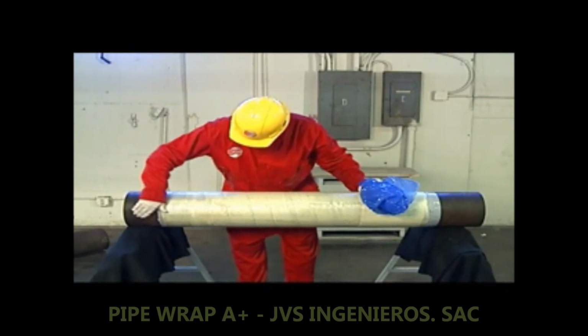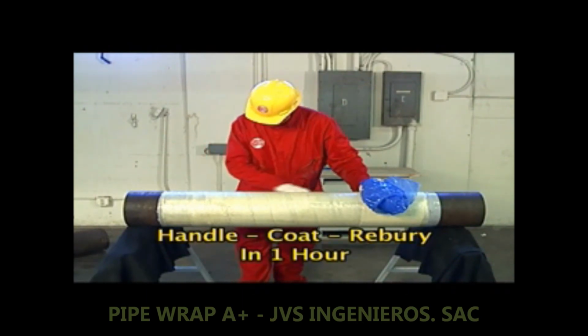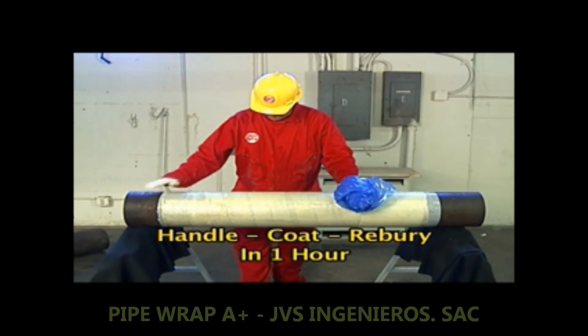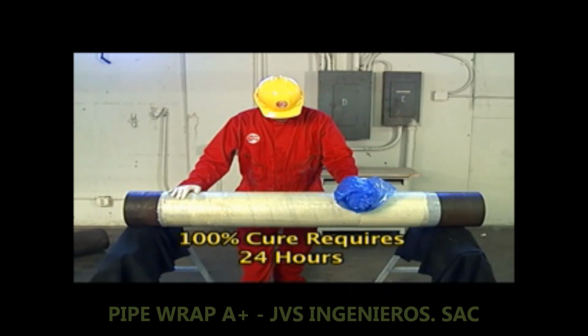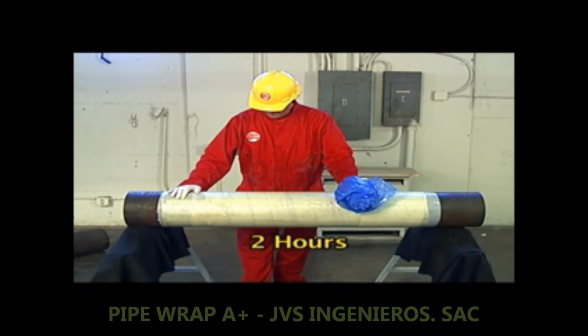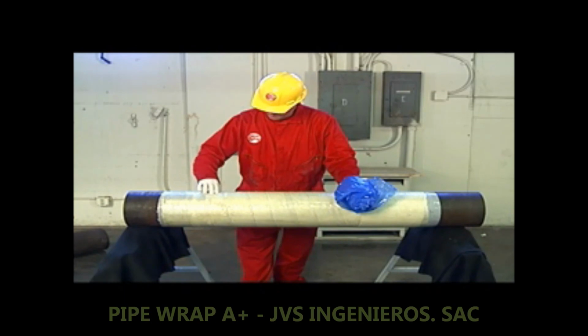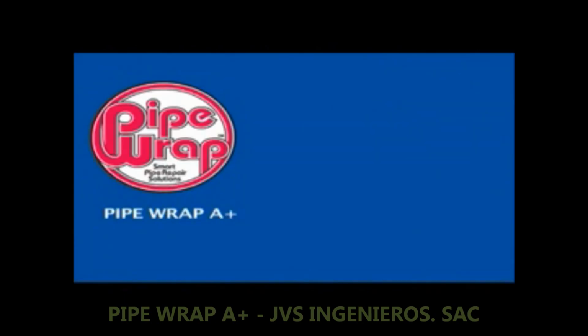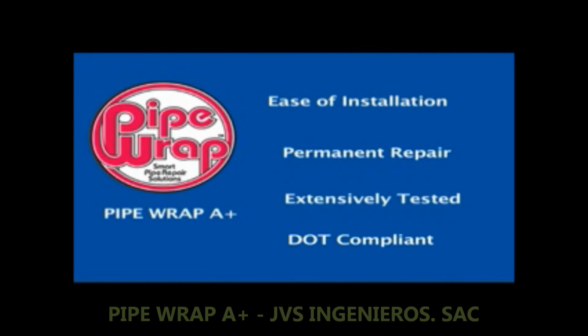Under most conditions, Pipe Wrap A+ will set enough to handle, coat, or rebury in 1 hour, although 100% cure requires 24 hours. The pipeline can be safely repressurized 2 hours after completion of installation. The Pipe Wrap A+ composite repair system is easy to install while providing a permanent repair that has been extensively tested and is DOT compliant.